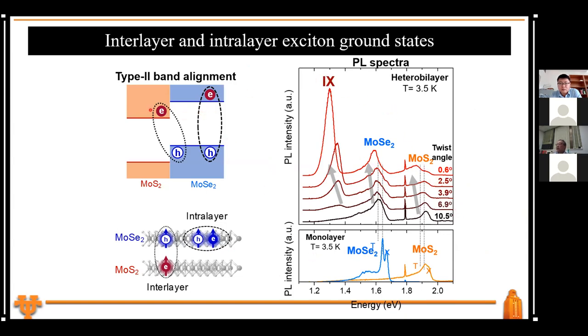Then we observe the interlayer exciton. So in this case, as a function of the twist angle, at large twist angle, they behave just like an isolated system. And then we go to the small twist angle, then the moiré pattern shows up, and then you will see a change of the interlayer exciton due to the periodicity change. So when the periodicity changes, even with the same moiré potential depth, the confinement changes. And you can measure the interlayer exciton here, and this is the intralayer exciton.